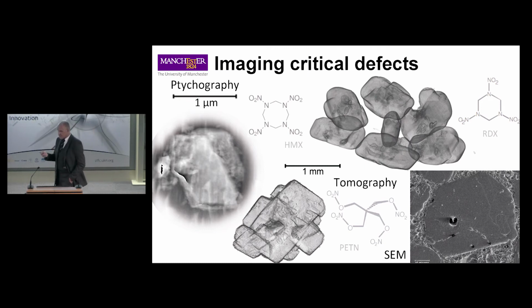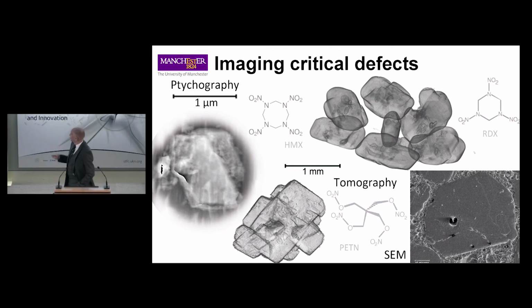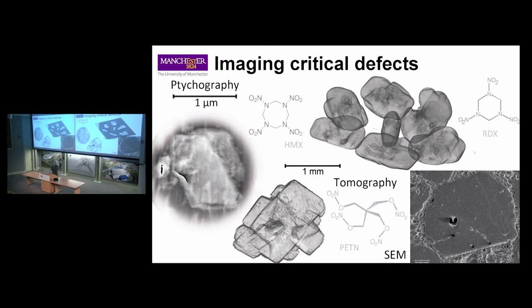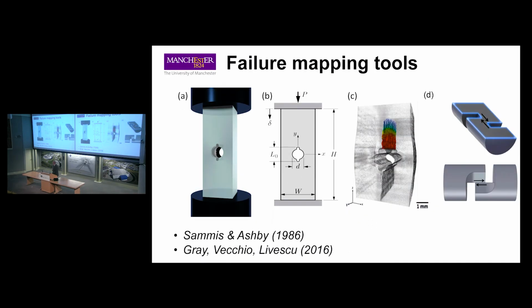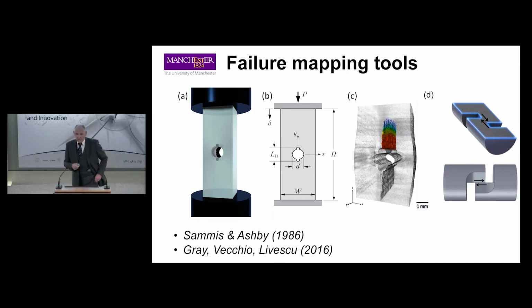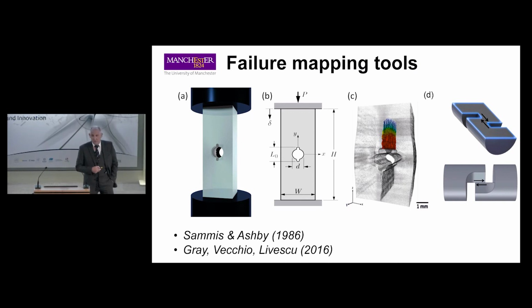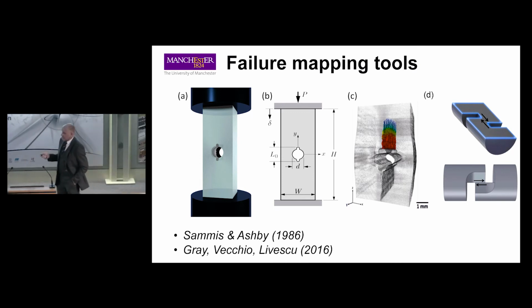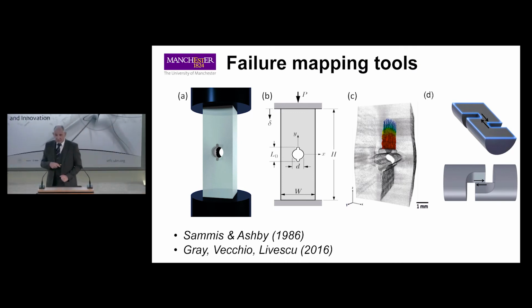So in principle, we can see the defects within our microstructures using the tools we have available. But can we see the critical ones? The beauty of an energetic material is if we excite the critical defect above its threshold, it'll start to react. So I want to show you now not only the failure that can occur within a particular geometry, but also results of that applied to a material that shows us how it responds.